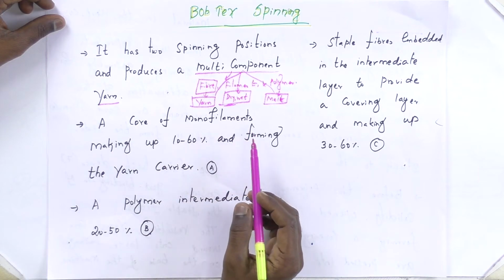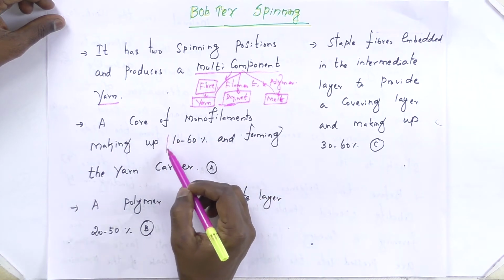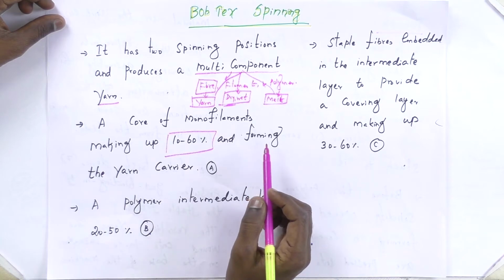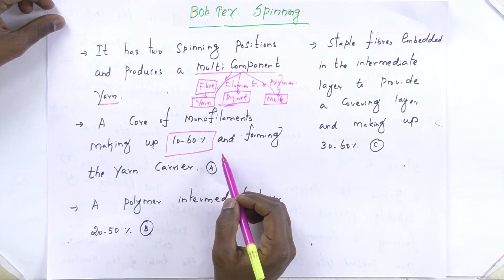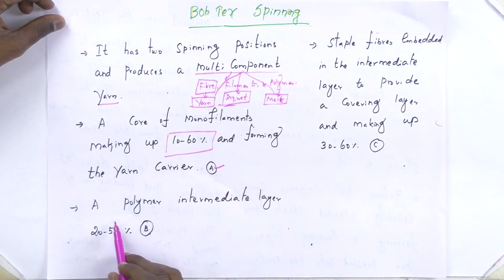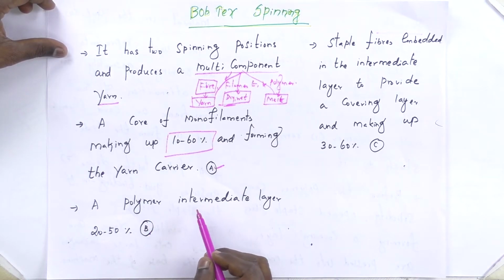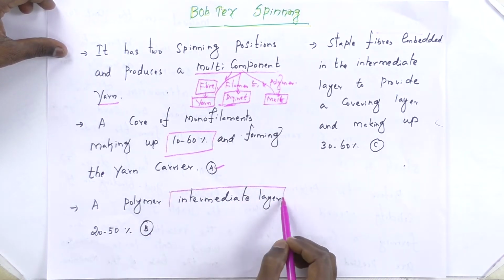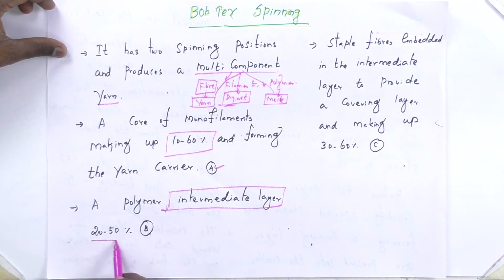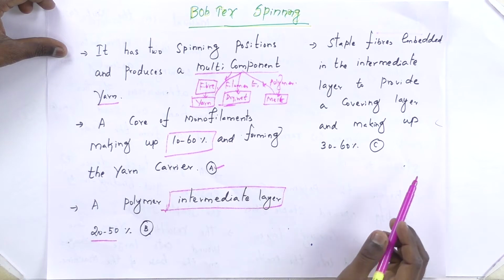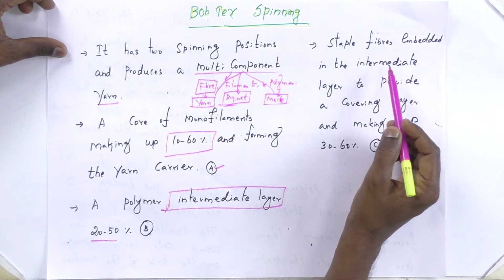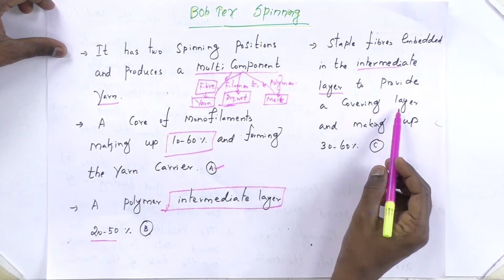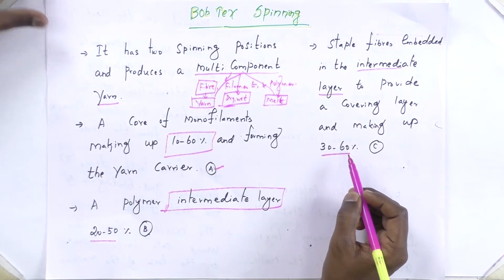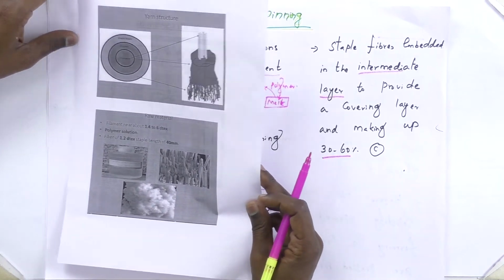Here a core of monofilaments makes up 10 to 60%. So the monofilament, in 10 to 60%, we are using for producing the Bobtex spinning yarn. It may be a yarn A. Second, a polymer which has a particular viscosity is used as an intermediate layer for making the yarn. It is used up to 20 to 50%. The third one is a staple fiber which is embedded in the intermediate layer to provide a covering layer, making 30 to 60%. So this diagram explains the structure of Bobtex spinning yarn.